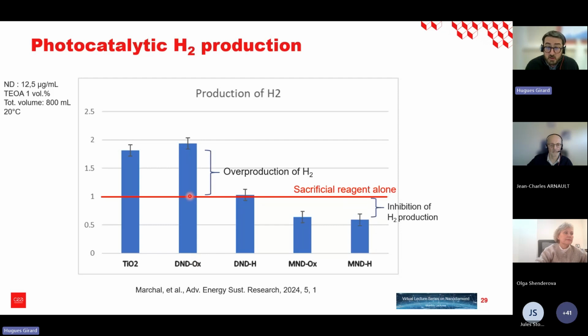And what was quite surprising at the time is that using hydrogenated detonation nanodiamonds, on which we could have expected some more fancy features like the solvated electron production and so on, finally we don't have any overproduction of hydrogen. What you see is that there is no production above the background of hydrogen due to the oxidation of the alcohol, the sacrificial reagent.